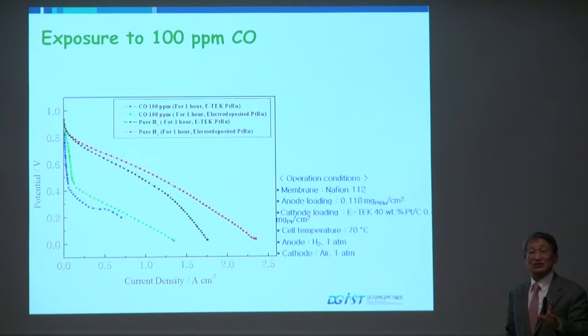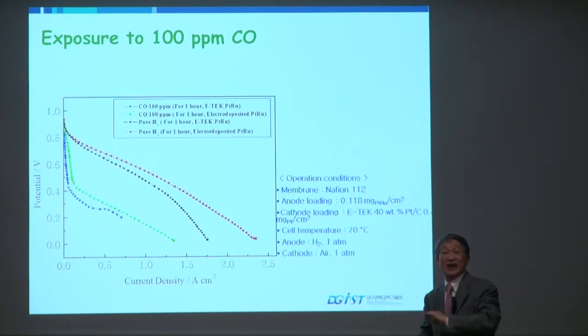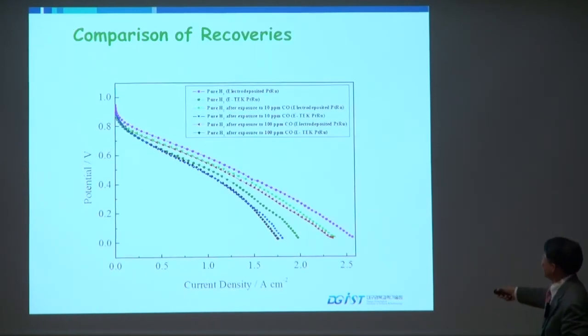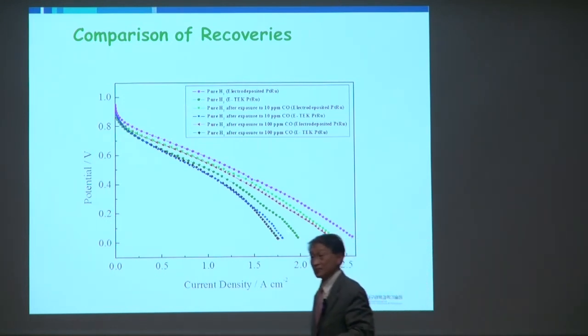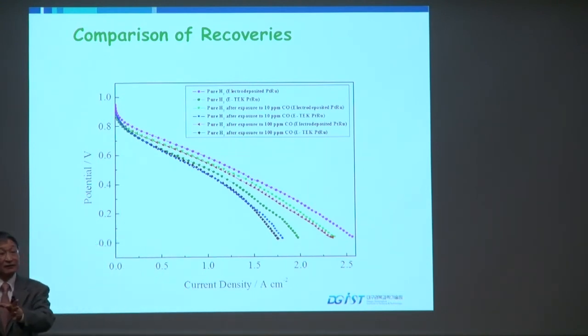Then, after this, we compare the recovery. After exposure to carbon monoxide, we look at how they return back to the originals. This is original, and those are 10 ppm and 100 ppm, and this is the same for this. Always, the electrochemically deposited ones return back. I mean, it doesn't return completely to the original. Some sites still contain carbon monoxide. But as you can compare, it always turns out to be better than the ETEC catalysts.